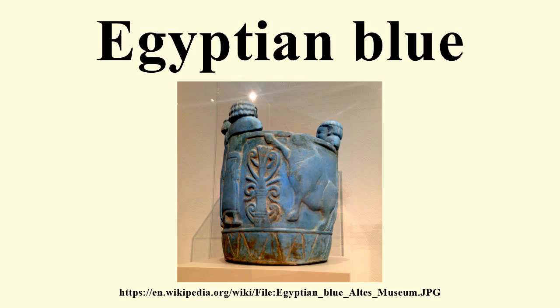The shade of blue reached was also related to the coarseness and fineness of Egyptian blue, as it was determined by the degree of aggregation of the Egyptian blue crystals. Coarse Egyptian blue was relatively thick in form, due to the large clusters of crystals which adhere to the unreacted quartz. This clustering results in a dark blue color that is the appearance of coarse Egyptian blue. Alternatively, fine-textured Egyptian blue consists of smaller clusters that are uniformly interspersed between the unreacted quartz grains and tends to be light blue in color.